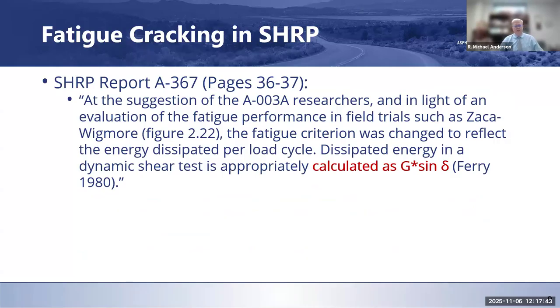So what did all that mean? Well, dissipated energy, and you can see up there as they talk about it, in a dynamic shear test is appropriately calculated as G star times sine delta. And so that's where that came from. That's why we've got this PG intermediate temperature criterion that we use on the DSR, this G star times sine delta property that reflects the dissipated energy that we have in an asphalt binder after it's been aged a